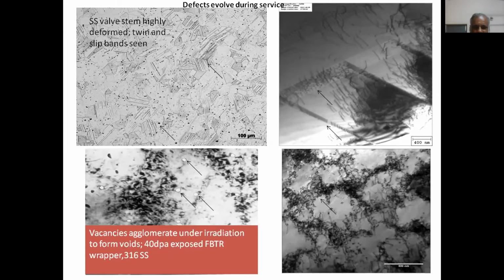So you could see the dislocations are getting scattered and going dark in the previous pictures. Here you find these round ones are basically voids, and these voids allow the electrons to pass through, and therefore the image is white. That is how you are able to distinguish them. You can count them, quantify them, and see how this varies as a function of several doses. Dose is actually measured in terms of DPA, like you measure money in terms of rupees. Okay, let me go into the next one.